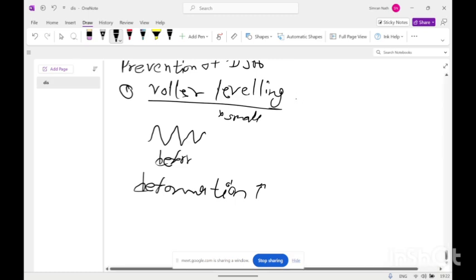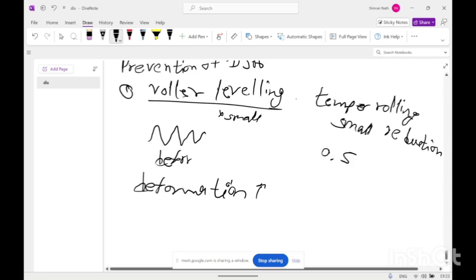Roller leveling, and second is the temper rolling. In temper rolling, a small reduction of the thickness is applied to the material, up to 0.5 to 1.5% of the thickness.